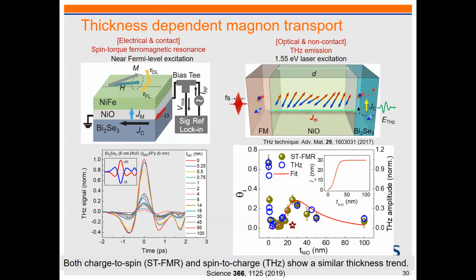So right now, if you look at our peak efficiency, it's about half of the peak without. So obviously, we lose some capability to generate, even though we minimize the shunting effect. Our efficiency is only half because the spin will go through two more conversion processes: you have to convert from spin to magnon and magnon to another one. So we lose some efficiency. That is the price we have to pay to use magnon. But of course, we hope we can find a system where the decay is small and the second peak will be almost the same intensity. That's our dream. Or maybe the second one will be even higher than the first. So that's the direction we want to study.